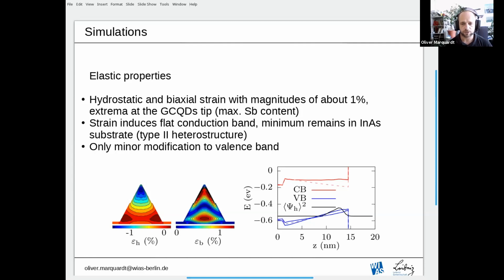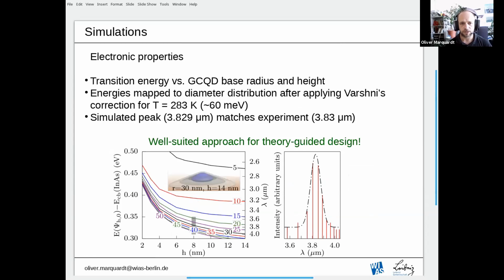And what we also see is what the strain does, if you have a look here at the band plots, the conduction and valence band structure along the central axis of this quantum dot. You see that the conduction band due to strain, that's the solid line here, is modified to something like a flat band, whereas unstrained it would be this dashed line. Valence bands are not affected too much. And what we see is then the hole states localizing somewhere here in the top of the system. I'll have a closer look at that. So that's the electronic properties.